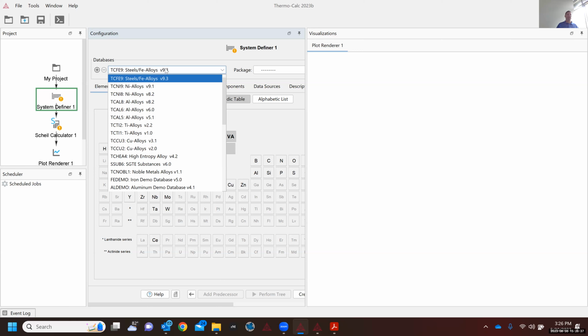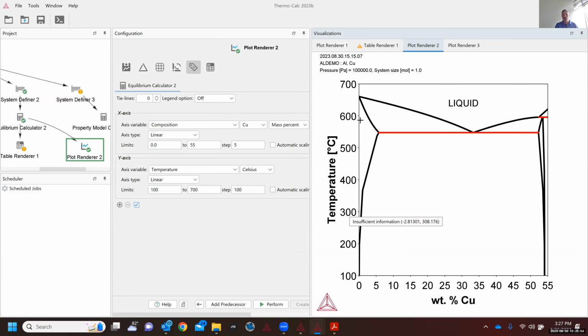Eventually, you'll go below T0, and you'll be able to solidify. So you may not actually see all of the eutectic, or you may not see eutectic, depending on what your starting composition is. But in a lot of alloys, even alloys in this aluminum copper system, and actually this 4% copper alloy that we started with, you might actually see eutectic solidification in the final microstructure. And I know that for some of these that are slightly above this maximum solubility, so a 6% copper alloy, you're going to see in an as-solidified microstructure eutectic FCC plus theta phase.